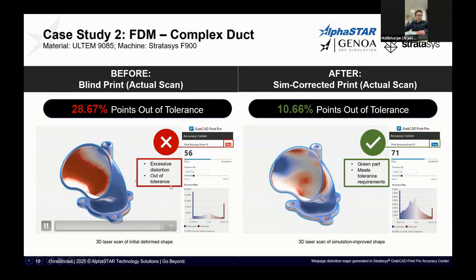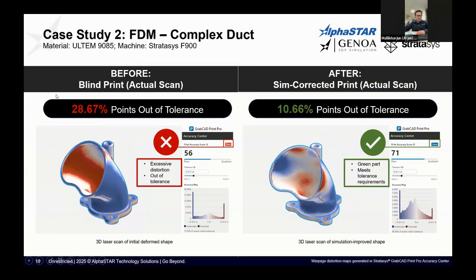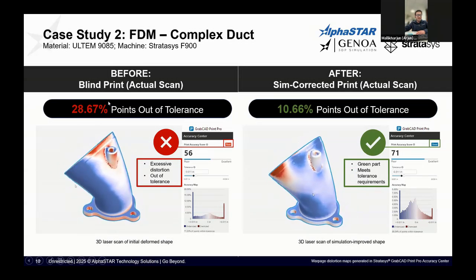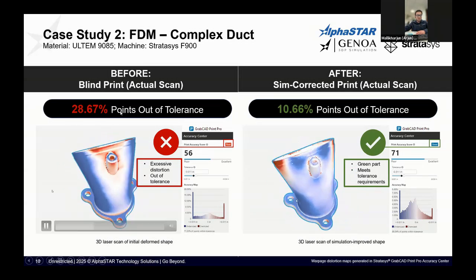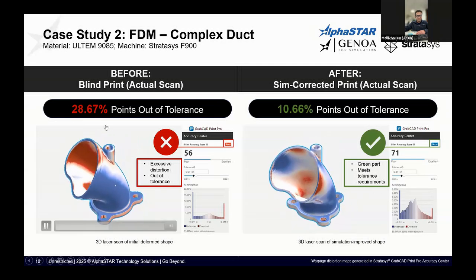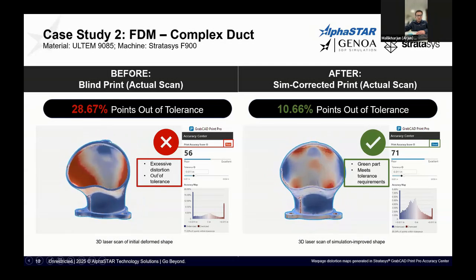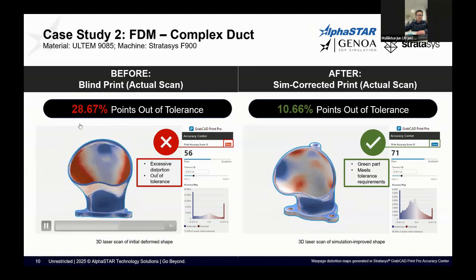So if we go with the blind route, you can see the out of tolerance values, 28.67% of points are out of tolerance, which means the tolerance we are comparing at here is 0.011 inches, which is about 280 microns or 0.28 millimeters. So at that given tolerance level, a lot of points are out of tolerance, and the points that are out of tolerance are way out of tolerance. It's not close to 0.011, it's way out of tolerance.